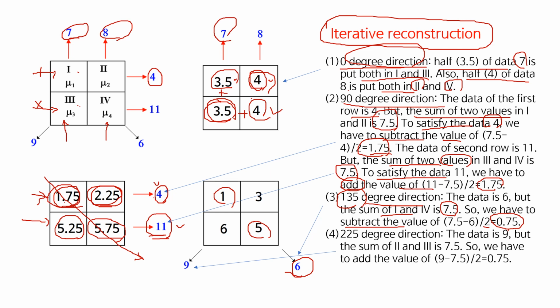And finally, the 225 degree direction, this direction, the data gives 9, but we have here 7.5. So the difference is 1.5, and half of that is 0.75. So we have to add 0.75 in this direction. So it gives 3 and 6. So we can have the same results shown in the previous slide. So using these values, we can construct the image by using grayscale.